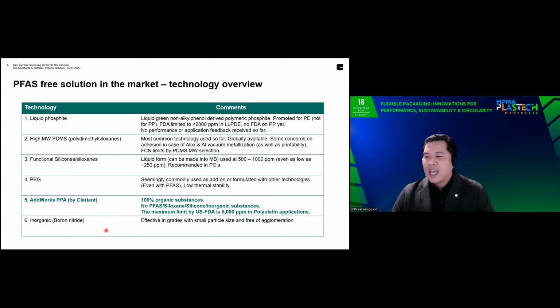For boron nitride, the user has to select the right particle size, because if they get the wrong particle size, it also has a tendency to agglomerate, and this agglomeration can make the film surface not smooth.